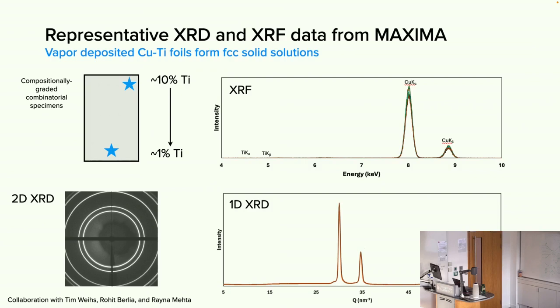So looking first at the X-ray fluorescence, here's the copper K alpha and copper K beta. There's actually several different samples on this plot, not just the two that I showed. You can see the copper quite clearly. You can see its intensity is changing as the composition is changing, but you can see that we have real difficulty in seeing the titanium. And again, that's because we're trying to do this in air.